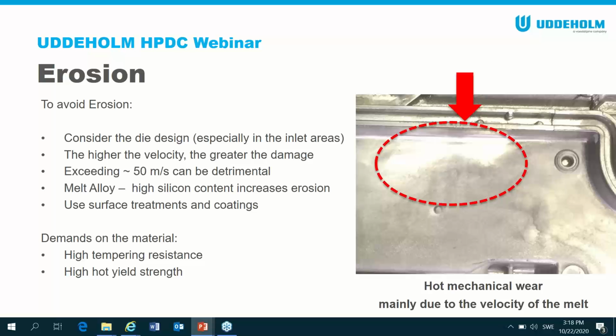So you have to consider the design when erosion is present, of course. If you've got a very, very thin gate with a lot of velocity coming through it, then you're definitely going to get washout erosion damage. So you have to consider the velocity and how much damage that's going to do. We tend to say if it's a non-vacuum assist die, 30 to 50 meters per second, that rough area. And if it's a vacuum die, then maybe 15 to 30 meters per second. Those are rough rules of thumb. It goes up and down, and different manufacturers have their own standards, but that tends to be what we say works quite well. You really, however, have to use a surface treatment here.